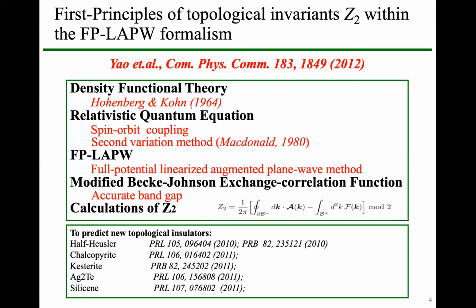So Wende, may I ask a question? Do you know what is the current status on the experimental side for silicene? Yeah, for silicene, there are already some experimental reports about the preparation, but any transport measurement is still not possible at the moment, because they usually prepare silicene on a metal surface, which means the topological edge state might interact with the substrate, and it's not possible to directly measure the transport property. It is also very difficult to transfer it to any insulating substrate. So this seems to be a very difficult work at the moment.